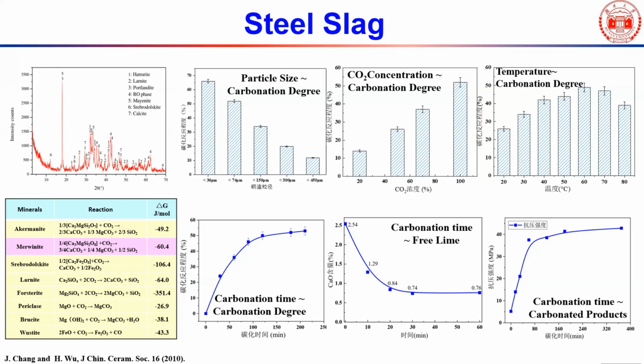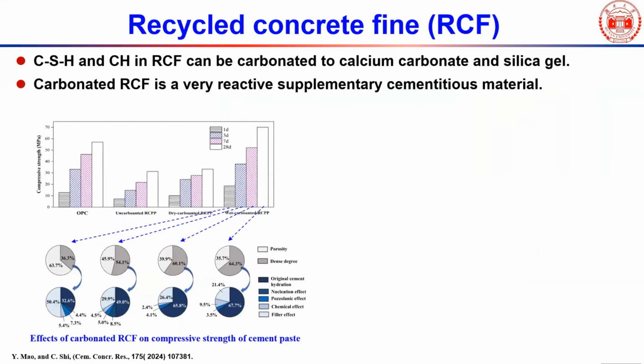But he did get some very good results, and we threw in some chemical admixture to enhance the carbonation, and we can get a strength of 60 to 70 megapascal, to make a carbonated steel slag product directly rather than carbonating it to become supplemental cementitious material.